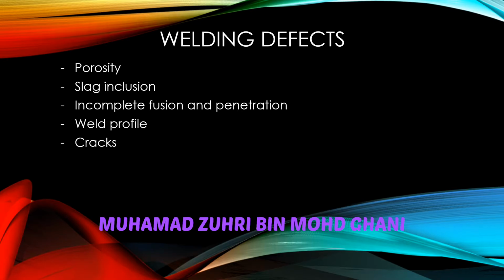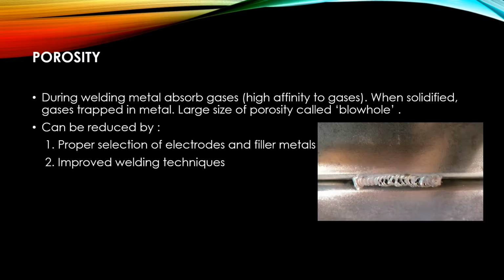Last but not least, the welding defects. It consists of porosity, slag inclusion, incomplete fusion and penetration, weld profile and cracks. For porosity, during welding metal absorbs gases, has a high affinity to gases, and when solidified, gas is trapped in the metal. A large size of porosity is called a blowhole. It can be reduced by proper selection of electrodes and filler metals, and improved welding techniques.